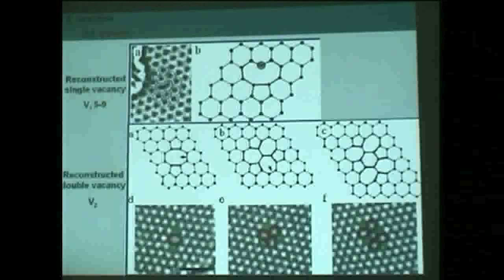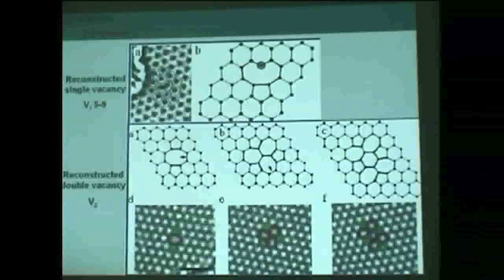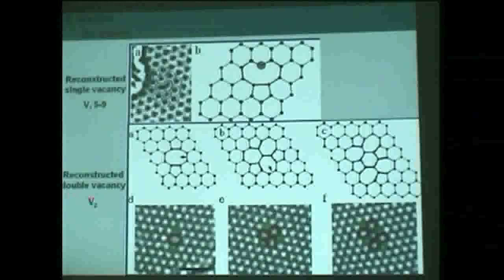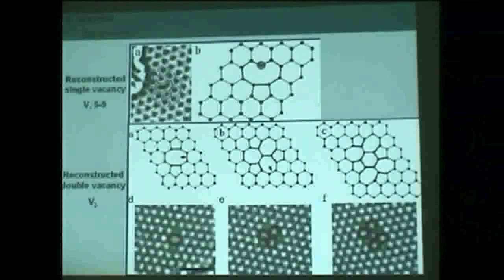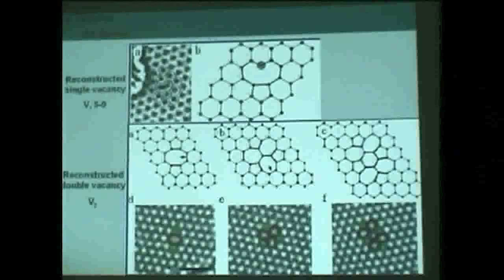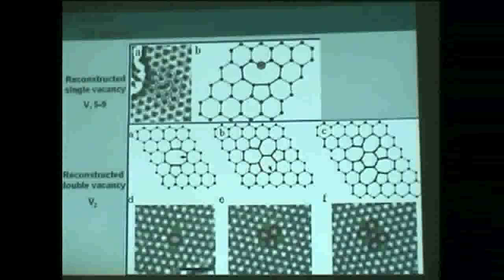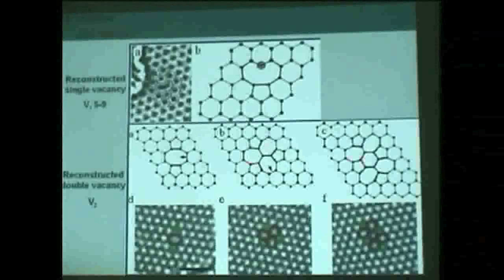Another example of reconstruction following the creation of a vacancy is this one. Here we removed, by the mind, 2 carbon atoms in the middle. Here also 2 carbon atoms were removed. And what happened is a reconstruction. The atoms created new rings, like a pentagon ring here. Another way is to create 3 pentagon rings and those heptagonal rings, and also this kind of structure.